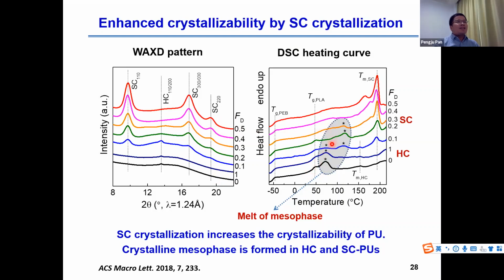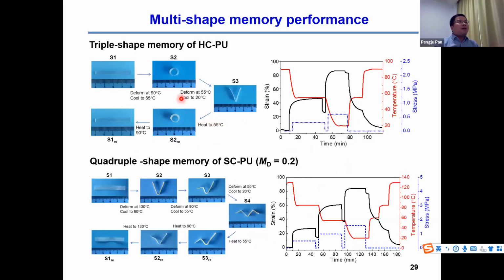We can see an additional melting peak above the transition of PLA. This is due to the melting of the crystalline phase in the network. The glass transition and the melting of the crystalline phase give the material a broad thermal transition in this temperature range. We further use this broad phase transition to design multiple shape memory materials.